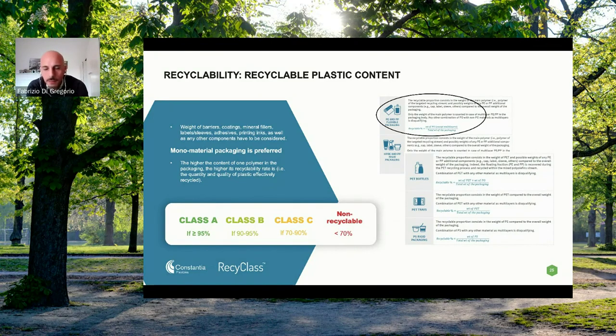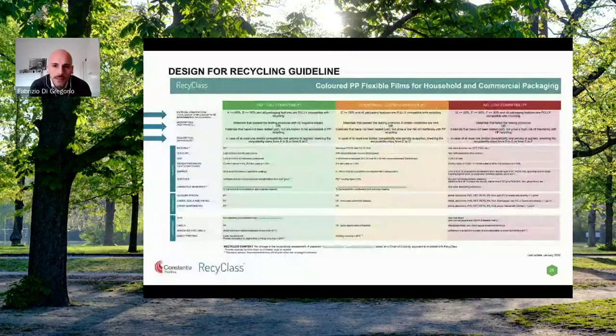Then, just as a second step, and we can move to the next slide, is a check on the compatibility with recycling. What makes the RecyClass guidelines a little bit special is that, on top of the guidelines, in the first three lines, you have the description that the guidelines are related to testing protocols. So the recommendations are not coming from me or from Hakim or from Martin, but really from a value chain collaboration carrying out tests with standardized testing procedures. There is a description of the methodology we are using to link the guidelines with the A to F recyclability score.